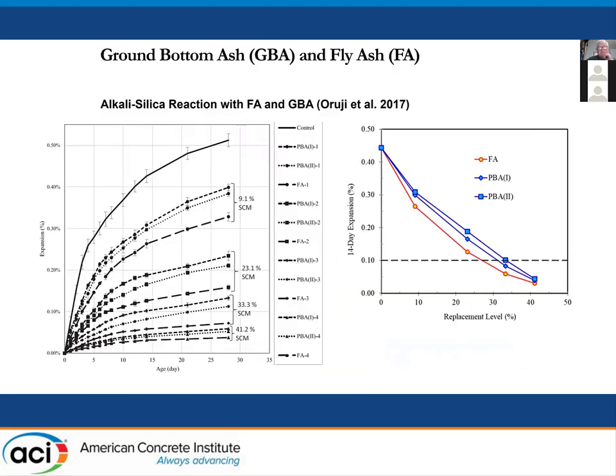Some ASR data with fly ash and ground bottom ash. This is a rapid mortar bar test that shows if you have fly ash and bottom ash, two different finenesses from the same source, you get essentially the same sort of reduction in ASR expansion at very similar levels. It's not identical, but it's very close, within a few percent.